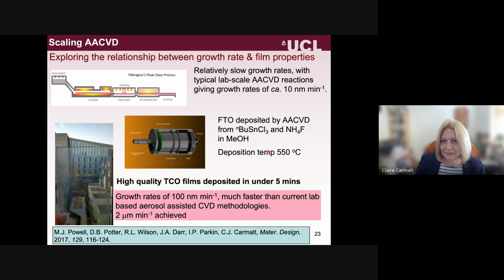And by changing to that collision atomizer that I mentioned right at the start, using much smaller aerosol droplets, we were able to reduce the deposition from half an hour down to 5 minutes, getting growth rates of 100 nanometers per minute. That's still not fast enough. So we have also looked at alternative nozzles where the aerosol is generated much more quickly. And then we have been able to achieve much faster growth rates of 2 micrometers per minute. So we're getting closer. We can deposit the film in around a minute. So we are still quite hopeful that this could be compatible with the industrial process.